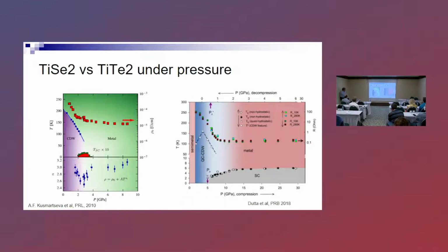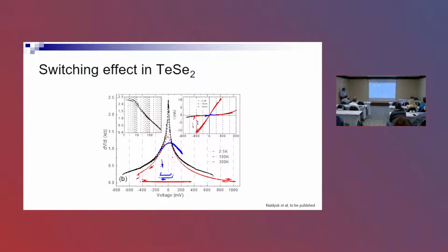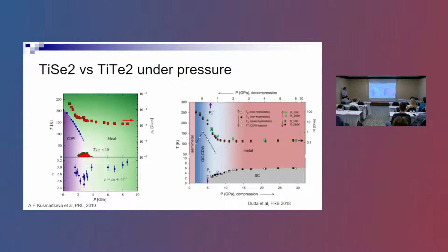So this is one of the reasons for our investigation, just to see if we have some low energy metastable state to which we can switch our material by the current or electric field. The second, we were also quite curious why, in the case of titanium diselenide, we have a charge density wave, which basically goes away with pressure. But if you look at titanium ditelluride, which is basically isovalent, we have no charge density wave.